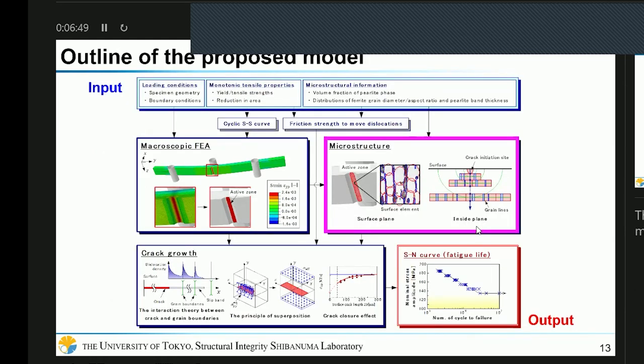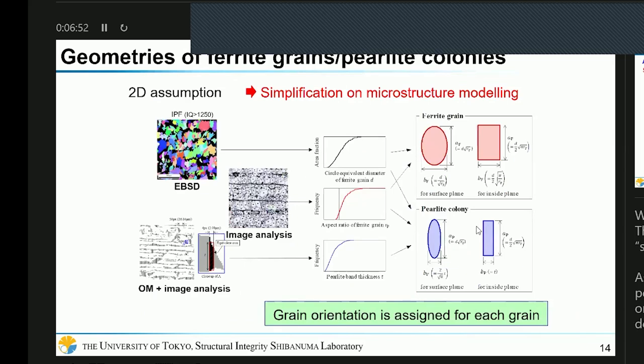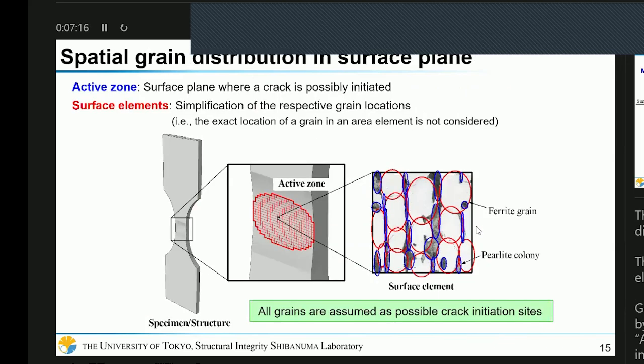And then the next one is the microstructure model. And as I mentioned, we assume a 2D problem with two steps. So this 2D assumption makes a significant simplification of the microstructure model. As a geometry of ferrite grains and pearlite colonies, we assume simple ellipses or rectangles like this, based on the size distribution of the microstructure. And this slide shows the spatial grain distribution in the surface plane. The active zone is divided into surface elements, and we assign each grain to each surface element like this. And all grains assigned in this surface element are assumed as possible crack initiation sites. This is our first 2D problem.